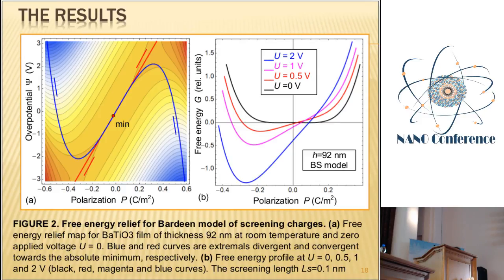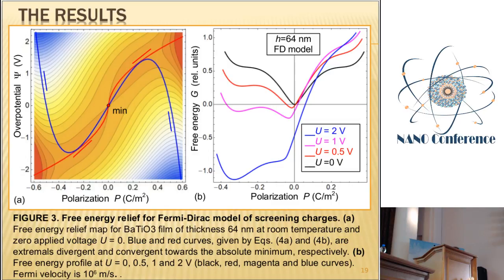For the second model, the Fermi-Dirac model of the 2D electron gas, you can see that, first of all, there are extremals, converging and diverging, blue and red, that are not close to one another, and unexpectedly the potential cross-section becomes not two wells, but one well with two local extremes. And when you apply external voltage to the film between the top electrode and the bottom electrode, one of the wells becomes deeper, it's okay, but the central well does not disappear at once. And there is some situation when you still have a two-well potential at big enough applied voltage. And maybe you have here some inflection point. This indicates that you can see the region of the double loops. And after one or two slides, I will show you this scenario.